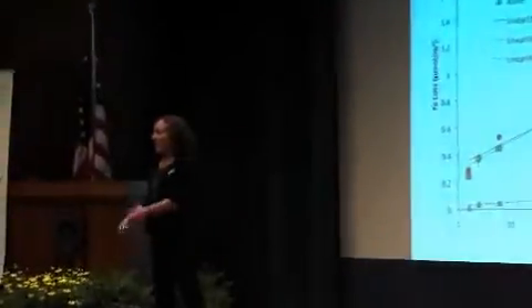And one of the things I really want to stress in this conference is that when you look out there at anything that anyone in my field is doing, a lot of times they're saying this is how nanoparticles react differently from slightly larger particles. But they're not normalizing for surface area in the experiment. They're correcting for differences in surface area afterwards. And they're seeing results that often are artifacts.